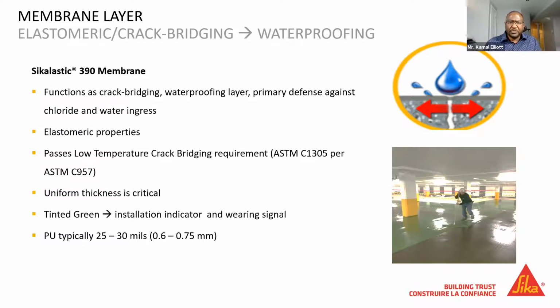So this is a reference to an ASTM test under C957 called low temperature crack bridging, where we cycle the membrane material through opening and closing at very low temperatures, -26°C, to ensure that the properties of the product are going to be intact even in cold temperatures. And obviously that's important for us here in Canada. Also important is that the thickness of the membrane is uniform. When they're applying it, they can't apply it at 5 mils over here and 40 mils over here. It really needs to be uniform to optimize the elastic properties of the material.